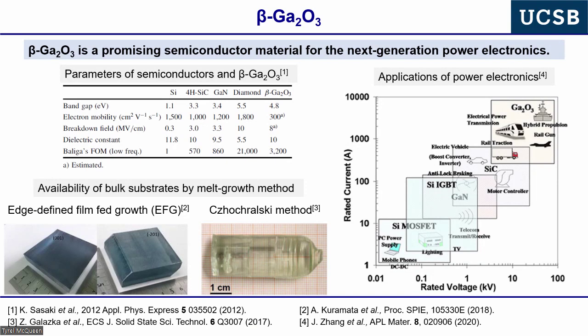The dielectric strength of a semiconductor goes something like the bandgap, maybe squared. That's not fundamental. And then we usually refer to this in something that's an ill-defined quantity, which is called the breakdown strength. If you look at silicon, it's about 300 kV per centimeter. So 1 centimeter thickness of material could hold up 300 kV. The silicon wafers are a fraction of a millimeter thick. This is why you have to have many, many silicon wafers stacked to get to the high voltages we referred to. And beta gallium oxide has a predicted dielectric breakdown strength on the order of 8 megavolts per centimeter. So this is about a factor of 30 times better than silicon, and about a factor of 2x or 3x higher than the competing wide bandgap semiconductors, silicon carbide and GaN.